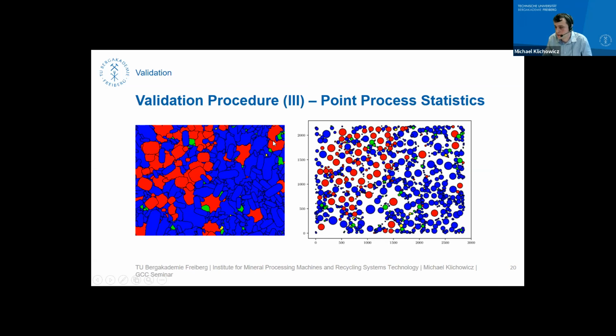So we just replace the real microstructure or the simulated microstructure by this point pattern. And for such point processes, there are statistics which are really standardized. And then we can work with standardized statistic methods to analyze whether we have realistic or not microstructures. And I will focus here on 3 approaches. And the idea of each of those approaches is that we take all points after each other. And if we have one point here, for example, if we have taken this point, then we analyze what happens in certain distances r from the point. So at the beginning, we look what happens at small distances r, and then we increase this distance until we have covered the whole image.